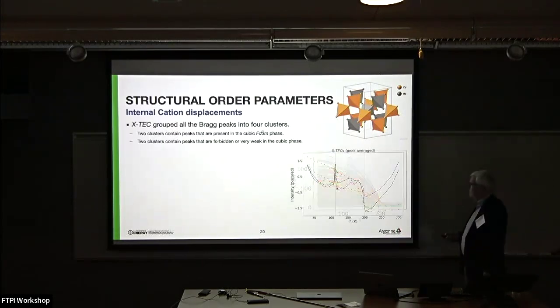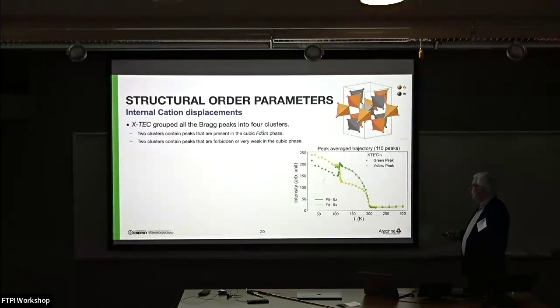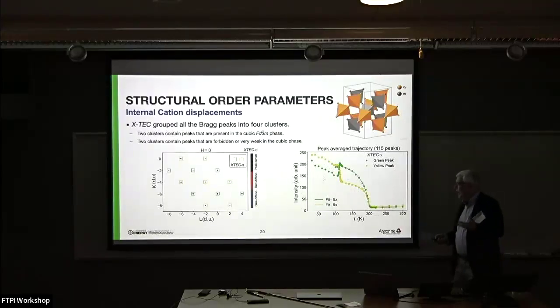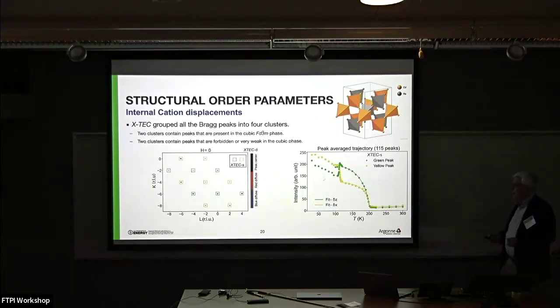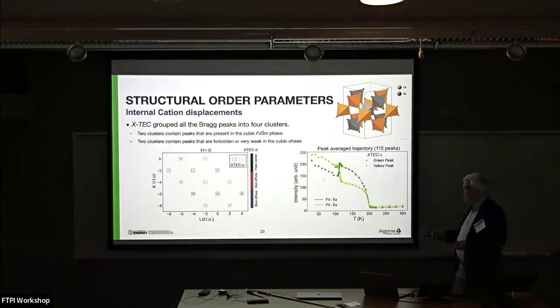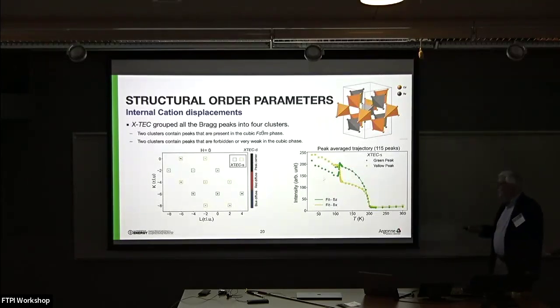So we did measurements over a lot of temperatures, and here are some of the trajectories thrown out by XTEC. I should have said XTEC is the name of the program that the Cornell group have written, and they identified 4 clusters. If I concentrate on just the 2 clusters of peaks which appear at the 200K transition, firstly you can see exactly where those peaks are in reciprocal space. You can also tell what their temperature dependence is, and in fact you can even fit critical exponents to these temperature dependencies.